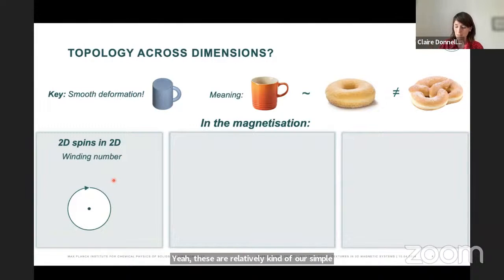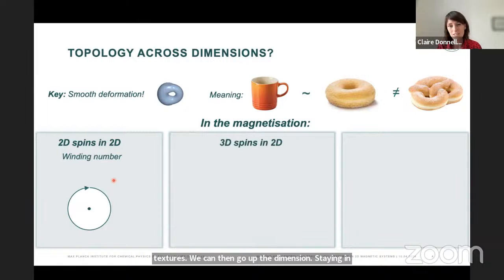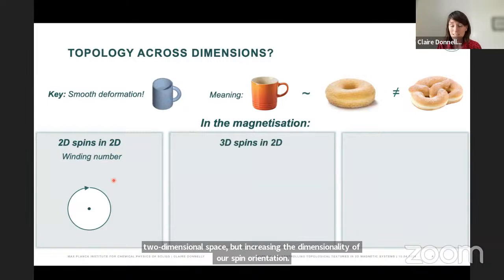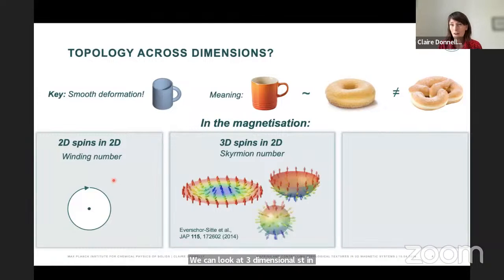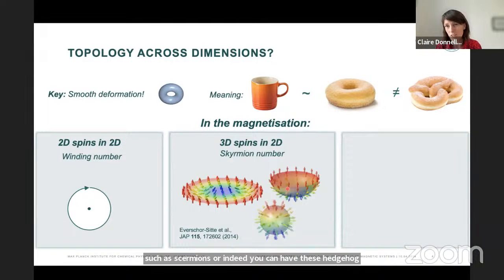We can then go up a dimension, staying in two-dimensional space, but increasing the dimensionality of our spin orientation. We can look at three-dimensional spins in 2D, where we now are looking at what's known as the skyrmion number, where by integrating over a surface, you can actually find these topologically non-trivial textures, such as skyrmions, or indeed you can have these hedgehog textures that are defined on a three-dimensional closed sphere in 3D space.